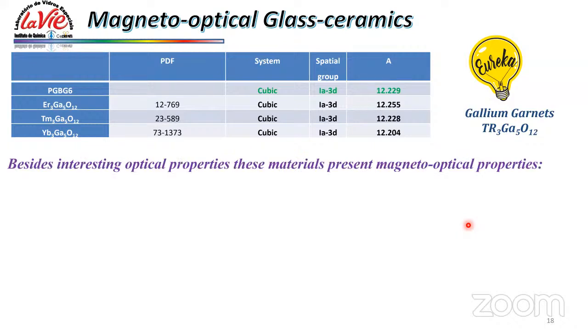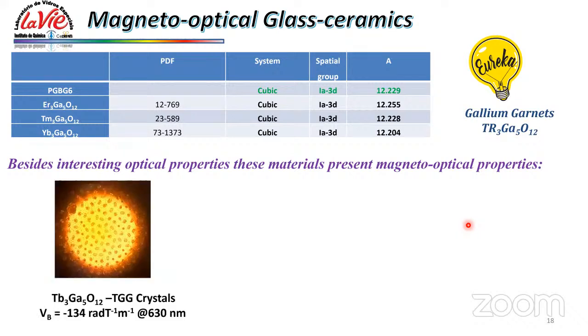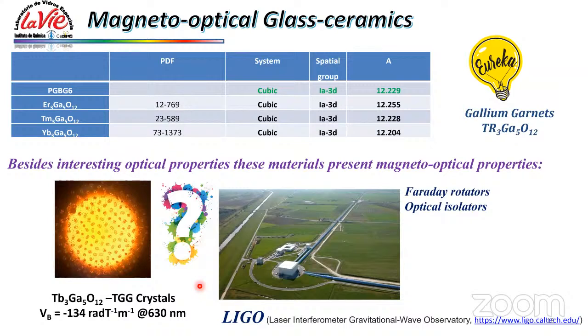The optical properties of these materials are interesting for us, but we thought, if we change the rare earths to terbium, if it was possible to get the TGG, the terbium gallium garnet crystals, which, as I told before, is the most used one in the market, with a Verdet constant of minus 134 rad per Tesla per meter at this wavelength. For example, one use of a TGG is in the LIGO, the Laser Interferometer Gravitational Wave Observatory.